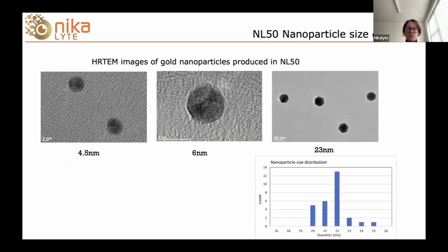Before I leave the topic of size control, I just wanted to show some TEM images of gold nanoparticles which have been generated in the NL50. You can see 3 different sizes here of nanoparticles produced just by changing the conditions: 4, 6, and 23 nanometers. The histogram underneath the 23 nanometer gold nanoparticles has been taken from the TEM image, so it's been taken after deposition. You can see there's quite a narrow distribution of just a few nanometers either side of the peak, showing the control and uniformity of size with the NL50.